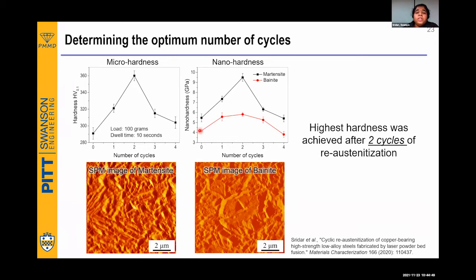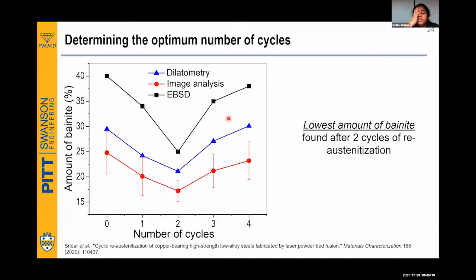Now, what is happening from the nano hardness is that there is a slight change in the bainite hardness. However, there is a notable change in the hardness of the martensite. And this is not something which is usual. So we probed further why this is happening. We tried to calculate the amount of bainite from different techniques like image analysis, dilatometry, and electron backscatter diffraction.